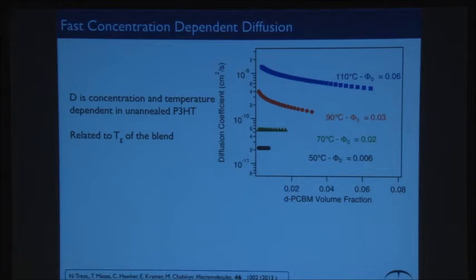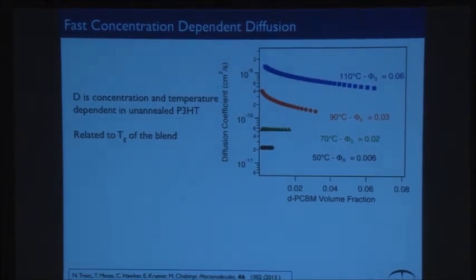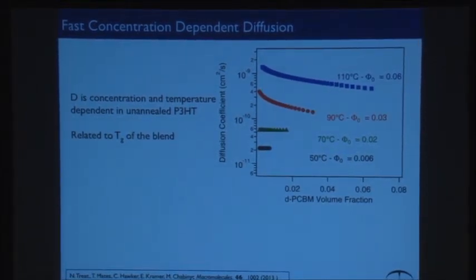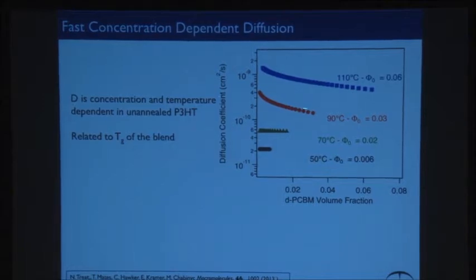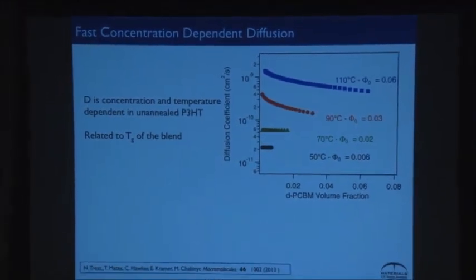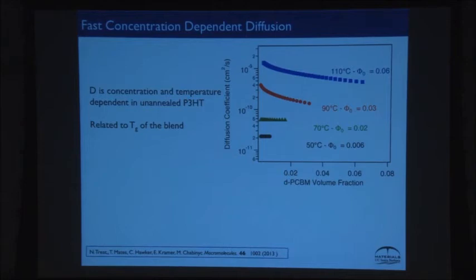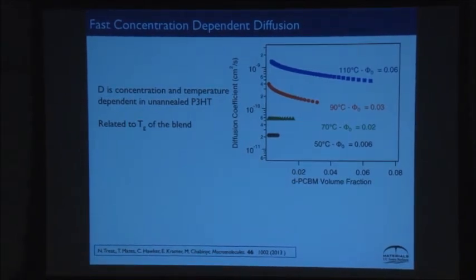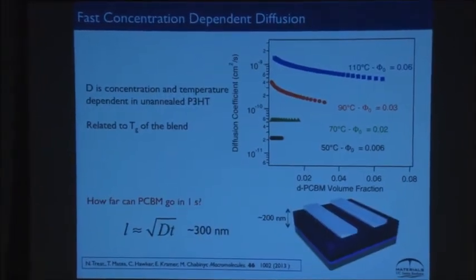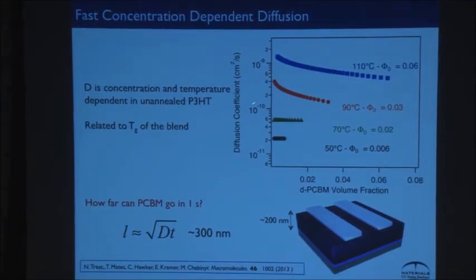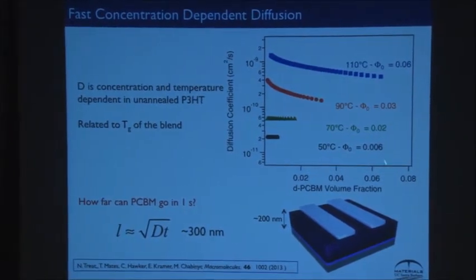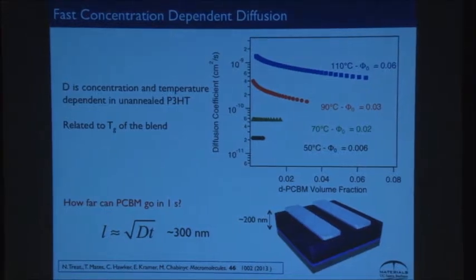And when you do this, you can now back out diffusion profiles, which I won't show you, that look reasonable, look Fickian. And then at some point, you hit a regime where you get Boltzmann-Matano type diffusion, where there's concentration dependence or volume fraction dependent diffusion, where we can see this as a function of temperature and composition now. And what we see is a quite strong diffusion, but it's fast, just like we predicted from our bilayer experiment. And just to give you a sense of this, if you don't look at these numbers all the time, that means when you're at these temperatures, the fullerene can go 300 nanometers in a second.